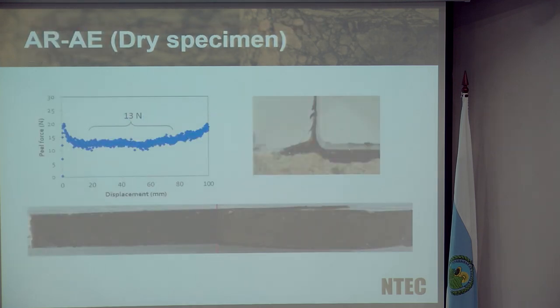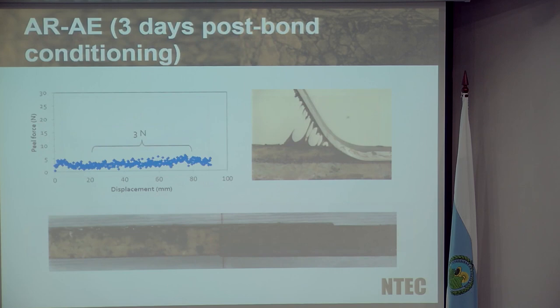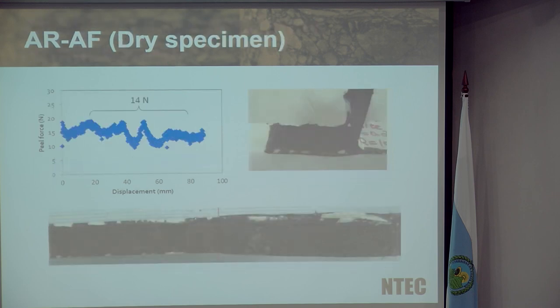Well, yes, we can. So what I'm going to show you now very briefly, just to finish off this section on the adhesion test, is those two aggregates that were effectively the same mineralogy, but with different diffusion rates. AE tends to be the one with a slightly higher diffusion rate. So it went from 13 down to 3 after 3 days conditioning. And AF tended to have a much lower diffusion rate. It went from nominally 13 again, slightly higher this time, about 14 newtons, but in terms of fracture strength, not that much difference once you've done the calculations.